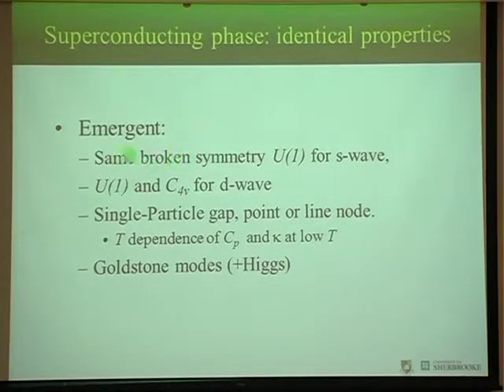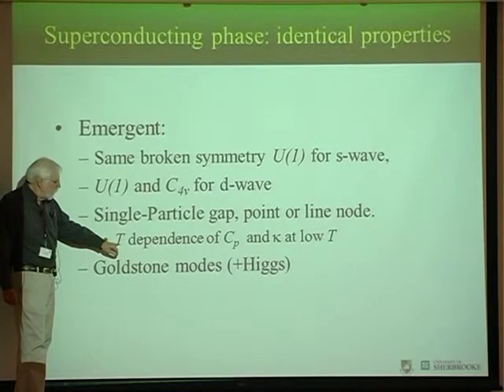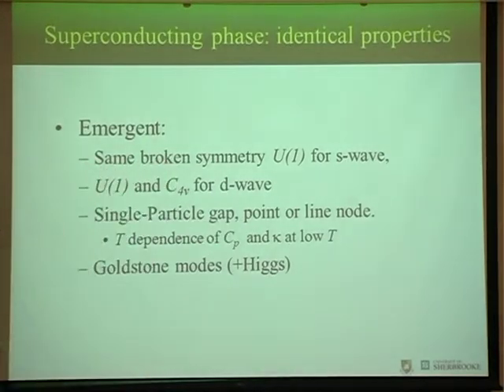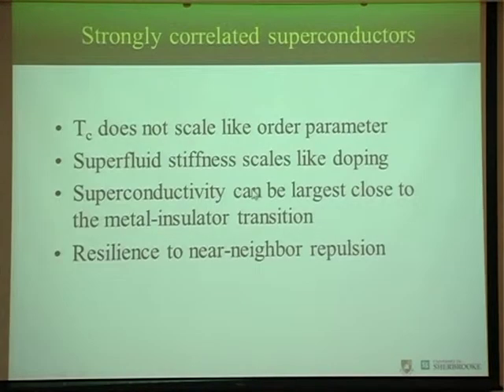Well, the emergent properties are the same, whether it's weakly or strongly correlated. So, for example, in the case of a D-wave superconductor, U(1) symmetry is broken, but rotation by 90 degrees is broken as well. There's a single particle gap and a point or line node, and that determines the asymptotically low temperature dependence of the specific heat, thermal conductivity, and various other properties, the structure of the Goldstone modes.